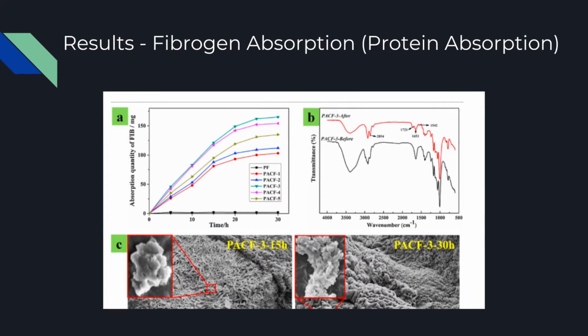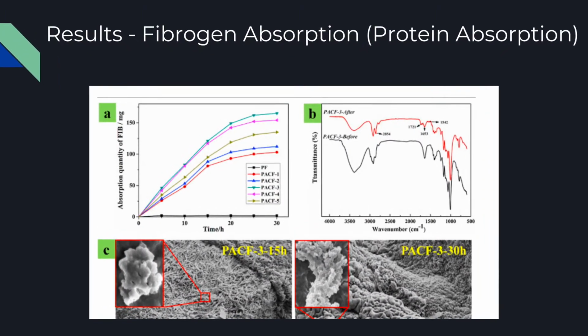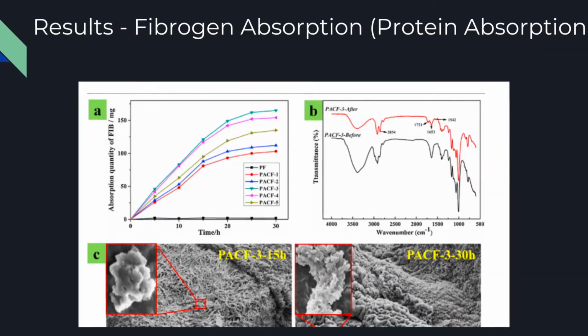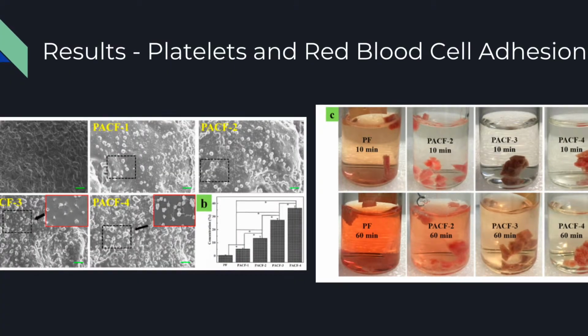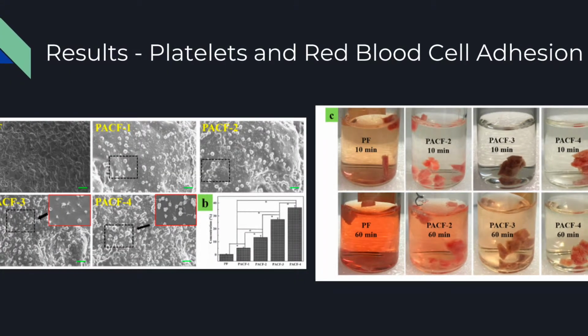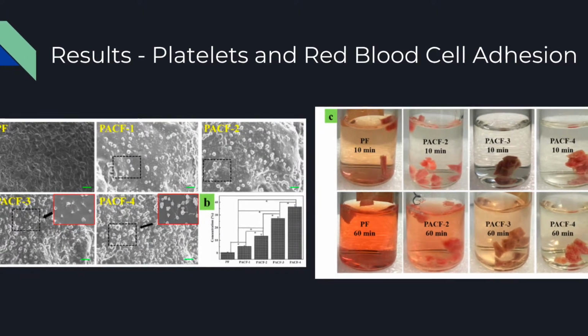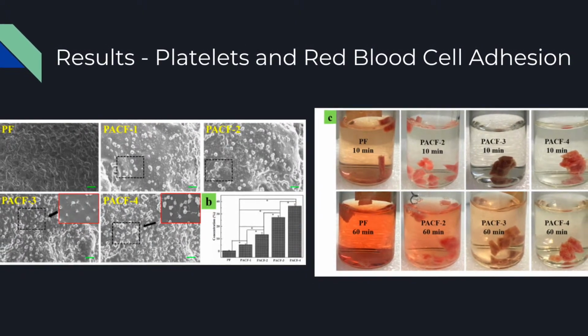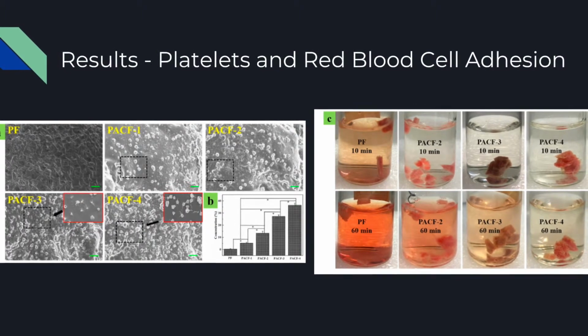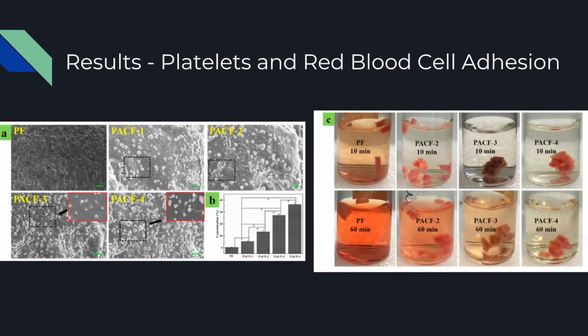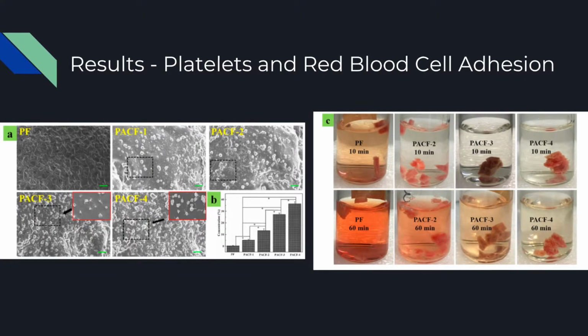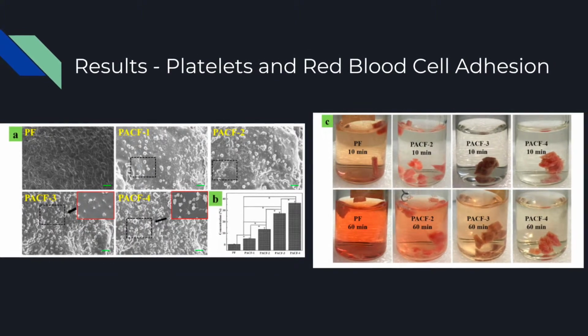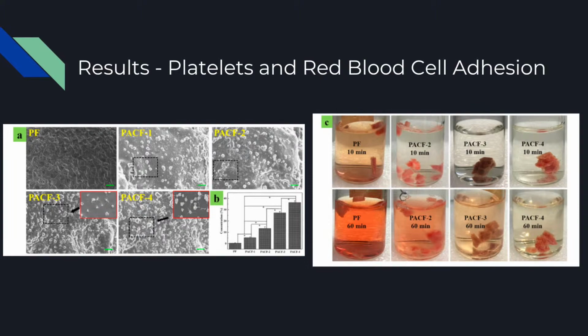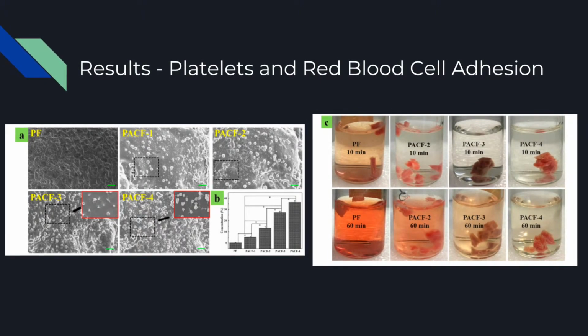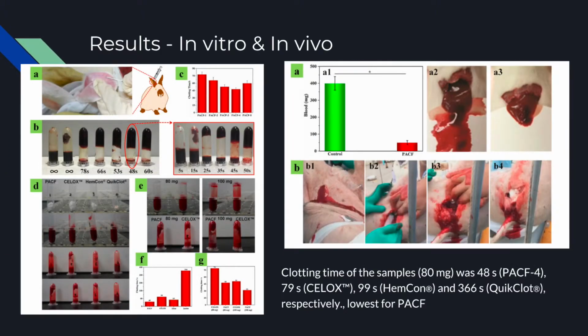PACF increased fibrinogen absorption, and protein fibers were seen on the surface of the PACF as well. There's no visible platelet adhesion on PF, but PACF3 and PACF4 had higher alginate and higher platelet adhesion. The solutions were also tested for red blood cell leakage, which can be visually seen and tested using spectroscopy for the absorbance of hemoglobin. And it was shown that PACF3 and 4 trapped red blood cells better and encouraged clot formation. The PACF was also tested in vitro and in vivo.